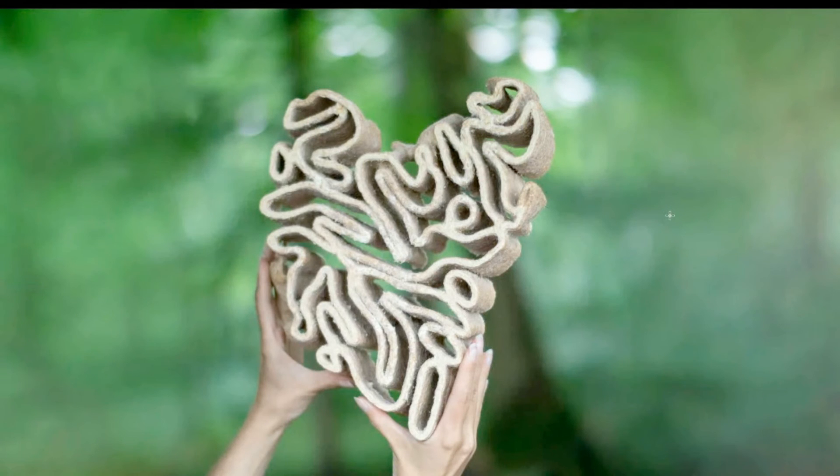Here is one of the components that is 3D printed. You can see air channels running through the components — at the single component level, these serve the purpose of ensuring oxygen access to the fungus. These folds increase the surface area on which the fungus grows, and more fungal growth means more biotransformation. This is only possible through 3D printing — unlike more traditional methods such as casting biomaterials, this ensures a much stronger material due to significantly greater growth.